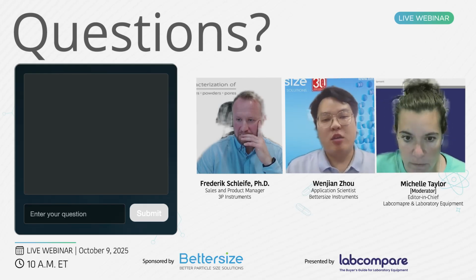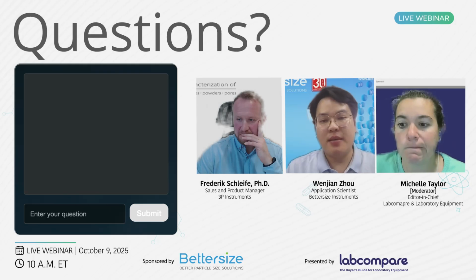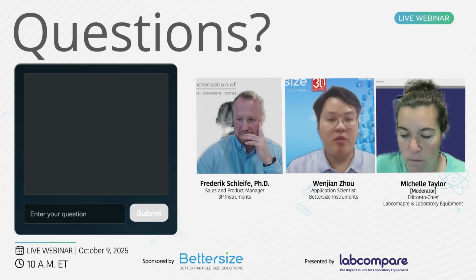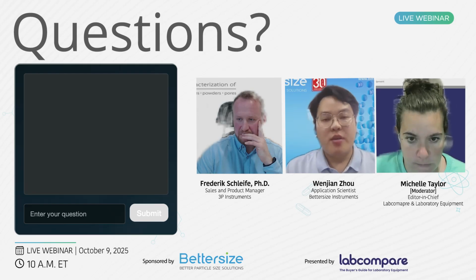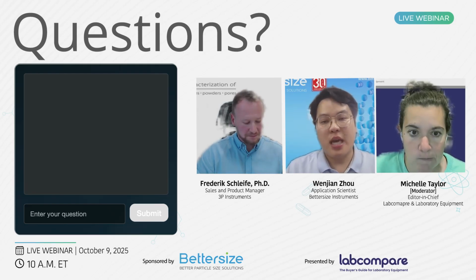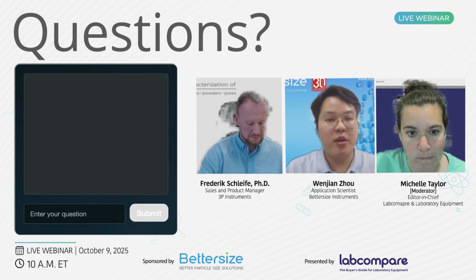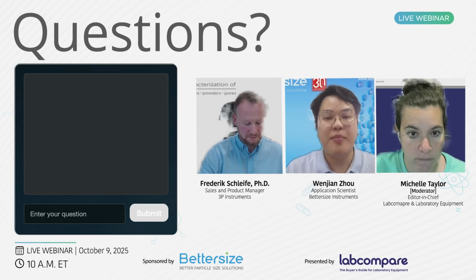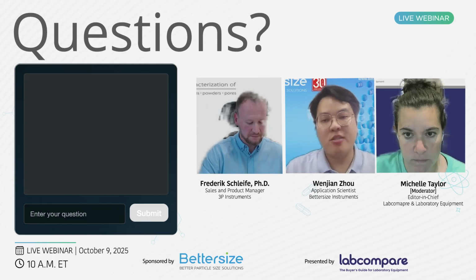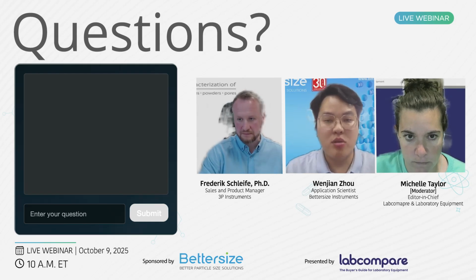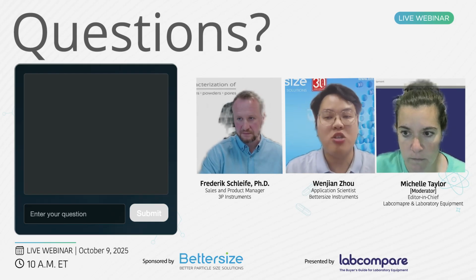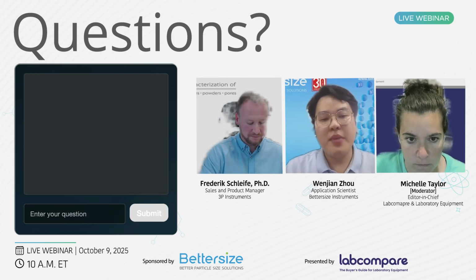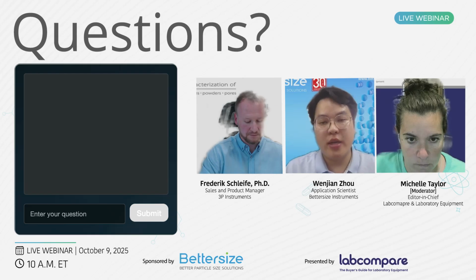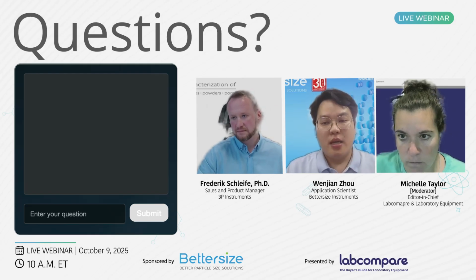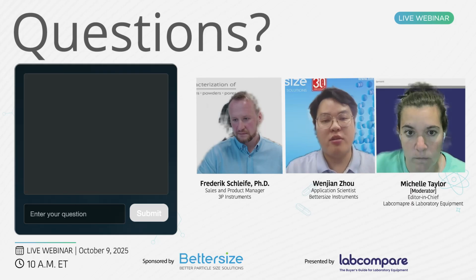Okay, helium is commonly used as displacement gas in a gas pycnometer for determining the true volume of ceramic materials. One of the main reasons is that helium is chemically inert, meaning it does not react with most types of ceramic or other solid samples. In addition, helium has an extremely small atomic size, which enables it to permeate into very fine pores and voids that may be inaccessible to larger gas molecules. This ability allows helium to provide a more accurate estimation of true volume, especially for porous or finely structured ceramic.